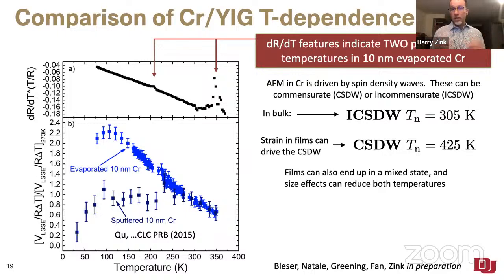But one thing that can clearly happen is that you can have just classical size effects that scale those temperatures down, right? And furthermore, a given film, dependent on the state of the strain that you have, can end up in a mixed state where you have regions with incommensurate spin density wave and other regions with commensurate spin density waves, right? So at the end of the day, for a given thickness of a given chromium film with whatever strain state you've got, you can have either a commensurate spin density wave, an incommensurate spin density wave, or a mix of the two, and the Néel temperatures of all of those different phases can be shifted depending on the thickness.